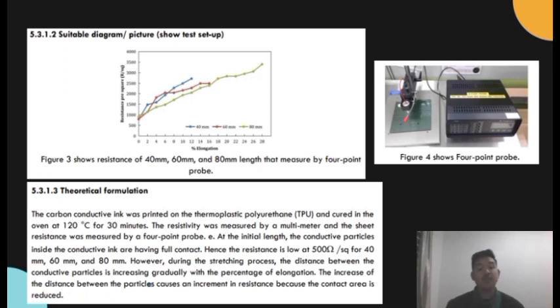Okay, the theoretical formulation is the carbon conductive ink was printed on the TPU and cured in the oven at 120 degrees for 30 minutes. The resistivity was measured by a multimeter, and the sheet resistance was measured by a 4-point probe. At the initial length, the conductive particles inside the conductive ink are having full contact. Hence, resistance is low at 500 ohm per square for 40, 60 and 80 mm. However, during the stretching process, the distance between the conductive particles increases gradually with the elongation percent.